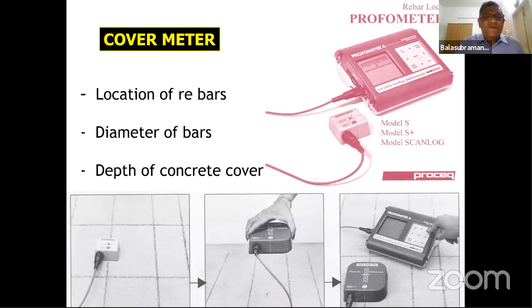This gives you the location of the rebars, and it also measures the diameter of the rebars. But there are a lot of limitations to this. A profometer will not detect a rebar if the cover is more than 70 mm. So that's a limitation. Suppose I go and put it on a column. Generally, what happens is while kinking, from one floor to another floor, if the levels are not okay, they try to kink the rebar and take it up. So on one side there will be 15 mm cover, the other side there will be about 80 mm cover. So when the cover is 80 mm, this will not detect the rebar.